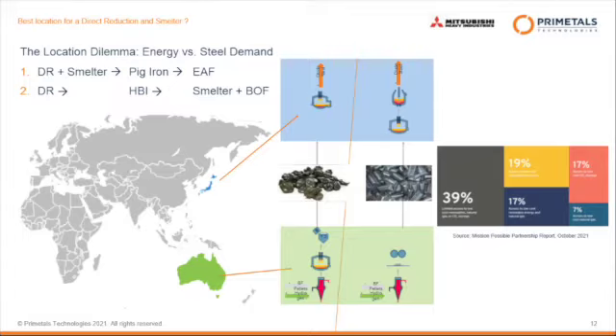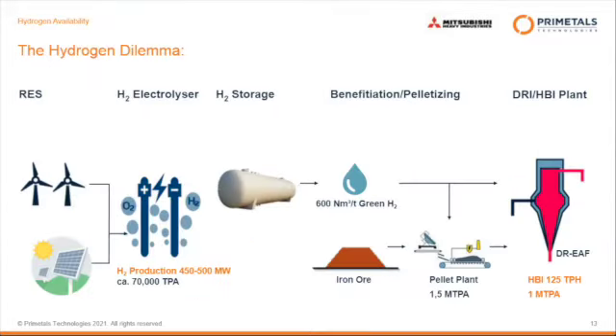And that's quite interesting. It requires different shipping rules. If you ship HBI having a lot of gangue, it requires certification of the procedure. So it has a strong impact. And why is it interesting? Because if you ship pig iron, meaning you put the melter still in Australia in that example, you have to granulate it. At the end, you cool it down from 1,500 degrees to ambient and ship it then. While if you ship HBI, you cool down the DRI from 600 degrees C, so you lose 600 degrees C, and feed cold HBI into the furnace. So it's an energy efficiency question, but on the other side, also an energy availability and energy price question. So quite interesting for the future. And that's the last slide.